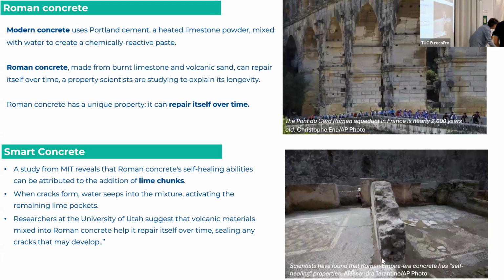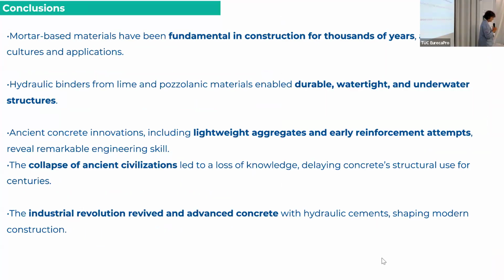And finally, what was discovered from specific and explicit studies under the scanning electron microscope is that this ability of Roman concrete was due to its possibility to repair itself over time. And this is totally due to some lime chunks that were inside the structure, and those lime chunks can function as activating points when it was a necessity and produce again calcite. And after this process, they help a lot in the repairing of this concrete over the years.